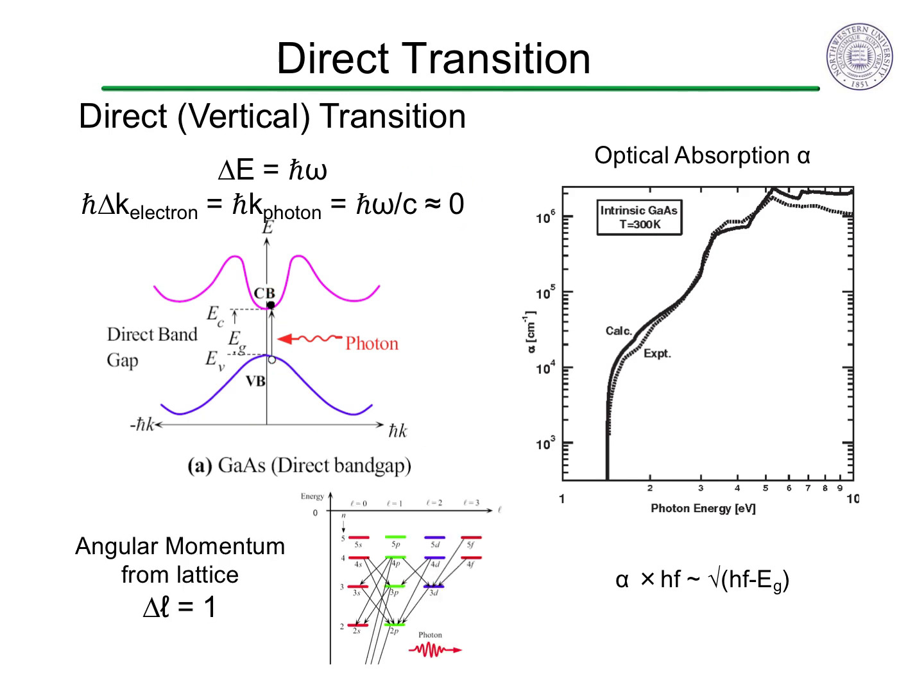The photon also has angular momentum that it can easily get from the orbitals in a solid, but this also makes SP and PD transitions higher absorption. The lowest energy transition will be exactly at the band gap energy, but there is only one state, so the intensity of absorption is low. At slightly higher energy, there are more electrons, a higher density of states, that can make a vertical transition in the E versus K diagram, so the absorption increases rapidly with some slope.